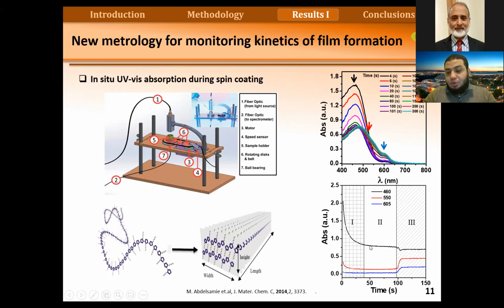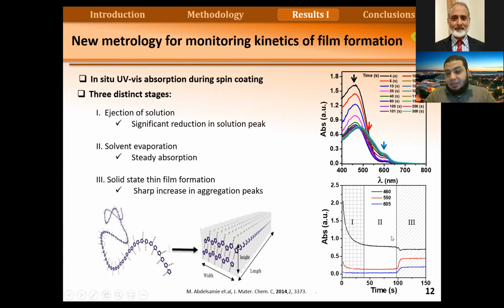This is amorphous. This is the solution peak, and the red and blue are the peaks of the crystalline film. So we can see here, we can watch the whole process. We can watch the solution leaving the film, and we can also see the final steps. We have three steps here. During spin coating, initially we eject a large amount of solution at the beginning, and then we get evaporation of the solvent, and finally we can see the solid state formation. Here the material starts to crystallize and form the final product. And the way we do spin coating can affect this process, like how much time is needed for this to happen.